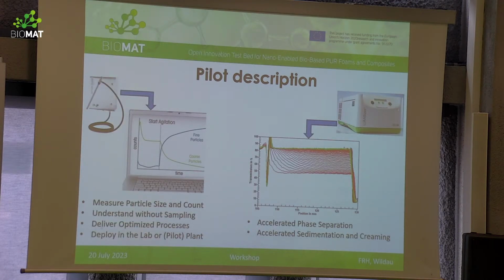Regarding analytical devices, I have spoken about inline controlling. We have this very good device from Mettler Probe, and this device allows measurement of particle size and count during the mixing process. We can understand the procedure without sampling, and we can optimize the mixing, velocity of mixing, maybe increasing or decreasing the temperature during the process. We see that we are not effective with these parameters, and we can at the same time change our parameters for increasing our effectivity. And this device, it's also very important, is useful for batches from 100 milliliter up to 100 liter. We avoid mistakes of the device. We use the same device for different volumes, for different batches.